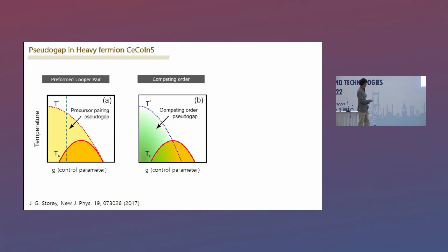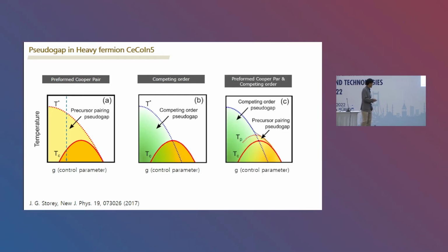On the other hand, if T star is the competing order, then you can see that the end point finishes within the superconducting state. If the system is more complicated, like you have both competing order and precursor pairing, then it's supposed to be more complicated, but yet it should finish when the Tc goes to 0.